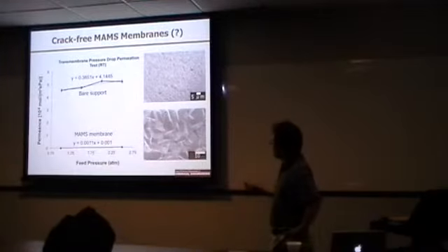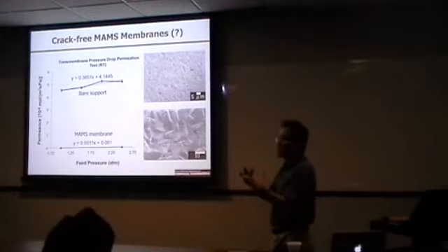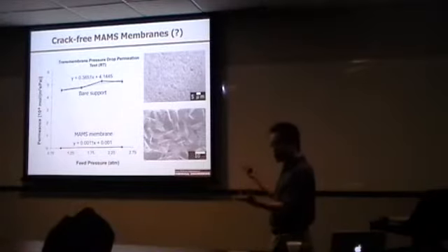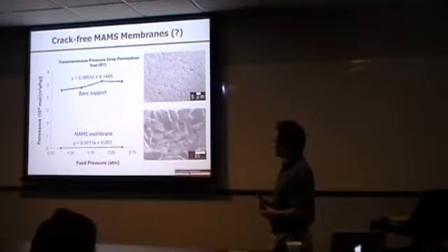But still, this is basically showing that we don't have macroscopic cracks. Without going into detail, we did the gas permeation measurement, but membrane performance was not that good. So I'm not going to show you the performance. The reason is because this is still fourth generation membrane, which means the pores are too big, because the measurement has been done at room temperature. Now, you may ask, what if we do the measurement at lower temperature?